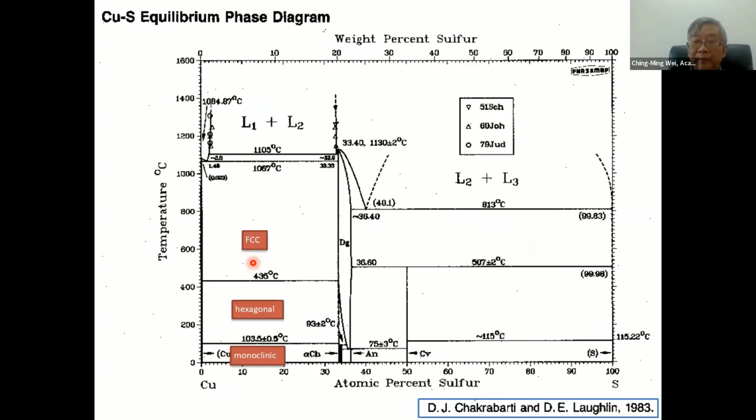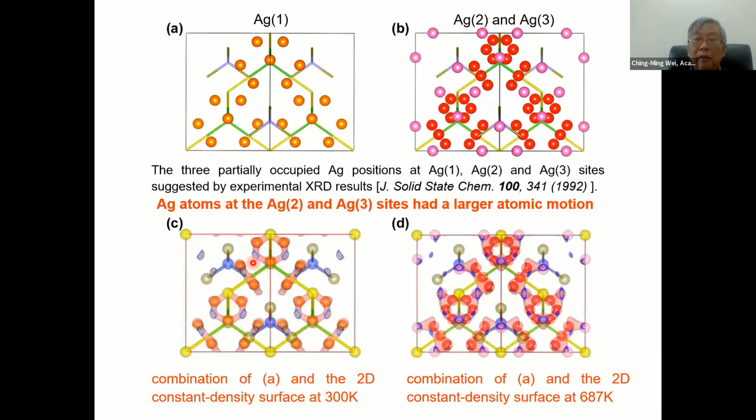So for this case, you run the MD simulation for a long time, and then you put all the atoms into the conventional or primitive unit cell, then you get a 3D atomic density distribution pattern, which gives you the very clear structural nature of the system.